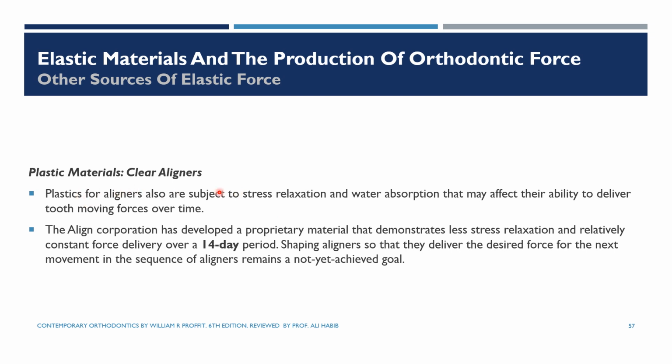In addition, one of the disadvantages of the clear aligner is that the plastics are subject to stress relaxation and water absorption that may affect their ability to deliver tooth movement forces over time. That's why Align Corporation, which is the company that created Invisalign, has developed a material that they claim demonstrated less stress relaxation and relatively constant force delivery over a 14 day period.